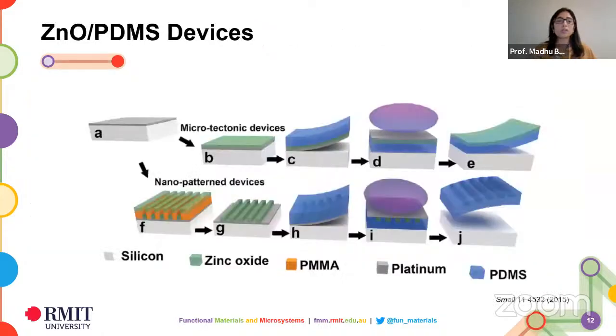Now, what I showed you was zinc oxide, indium tin oxide, but then we also thought, let's not stop at indium tin oxide. Let's see if this process can be used for other oxide layers as well. Now, this slide here shows you the process we use for creating zinc oxide on PDMS devices. It's exactly the same process. Nothing has changed in this case, except for the fact that we are using zinc oxide instead of indium tin oxide.